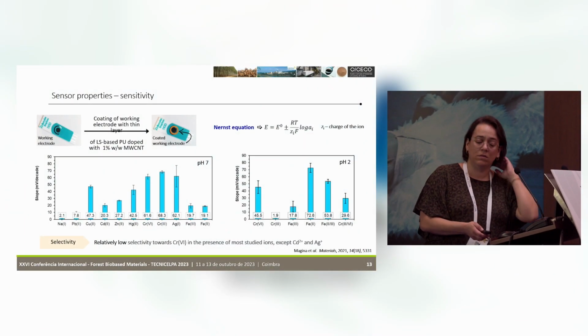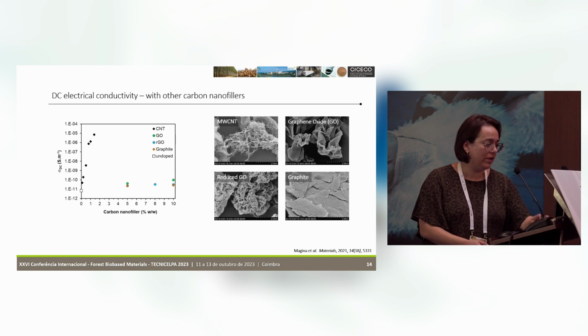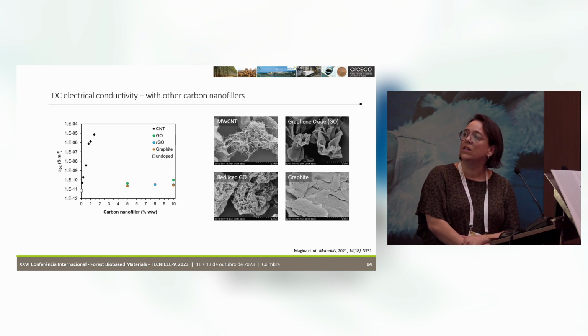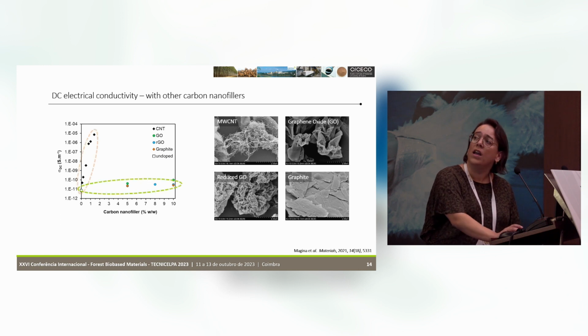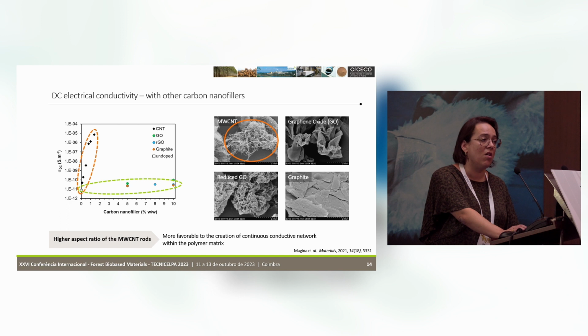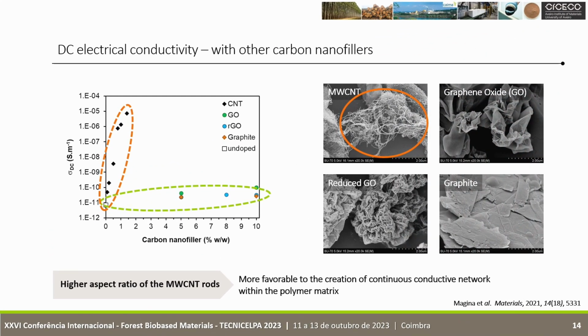...graphene oxide, reduced graphene oxide, and also graphite. As you can see, even increasing the amount of carbon nanofillers up to 10%, there was only a slight increase in electrical conductivity, so the type of carbon nanofiller used is really important, mostly because of the higher aspect ratio of the carbon nanotube rods, which are more favorable to the creation of a continuous electrical conductive network.